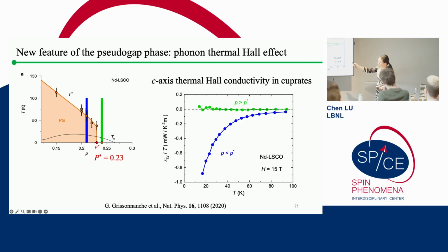I want to remind you that the particular type of cuprate material we started with is called Nd-LSCO, a hole-doped cuprate. And from the phase diagram, you can see the pseudogap phase, a very mysterious one. It ends at a critical doping called p star, about 23%. So what we found is that the pseudogap phase itself actually has a new type of feature, which is a non-zero phonon thermal Hall effect.